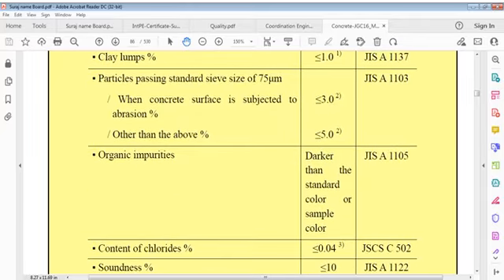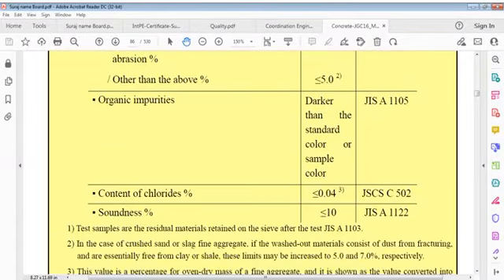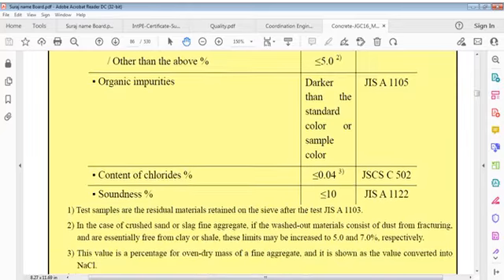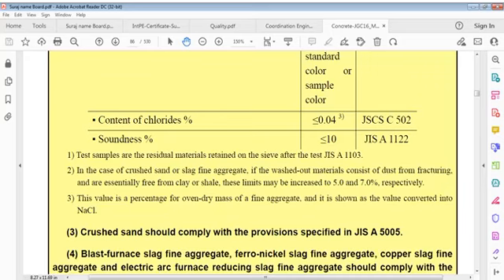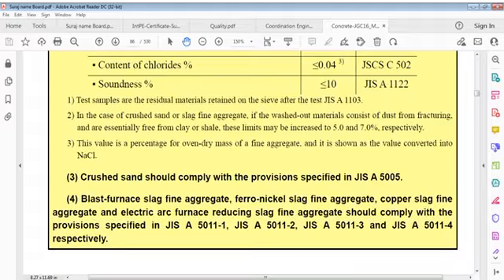Particles passing standard sieve size 75 micron: when concrete surface is subject to abrasion, less than or equal to 3, and other than above, less than or equal to 5. Organic impurities should not be darker than standard color or sample color, and of course chloride content less than or equal to 0.04, and soundness percentage less than or equal to 10. Test samples are residual materials on sieve after test.